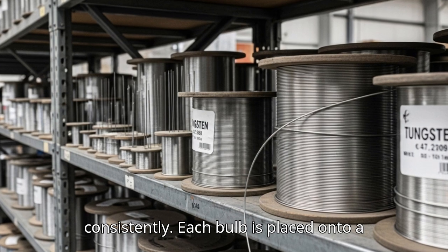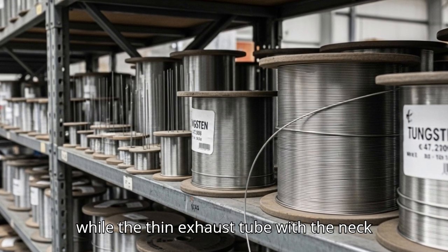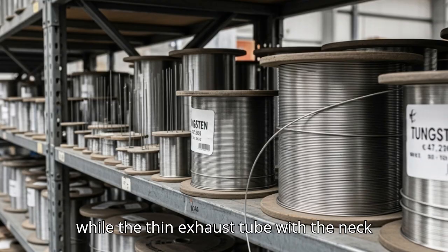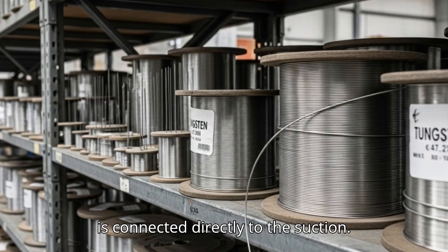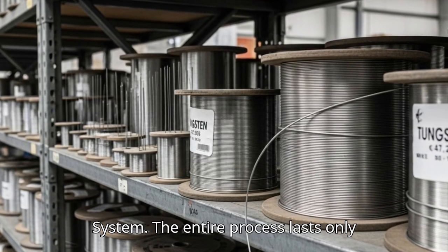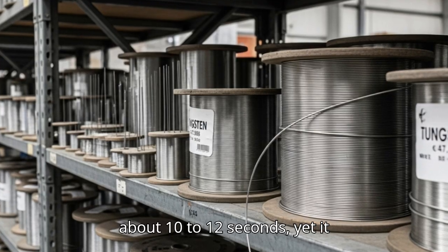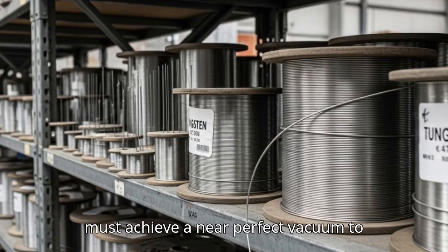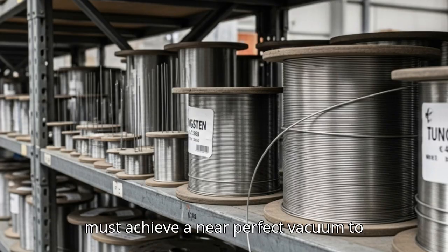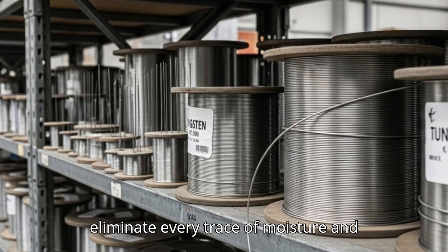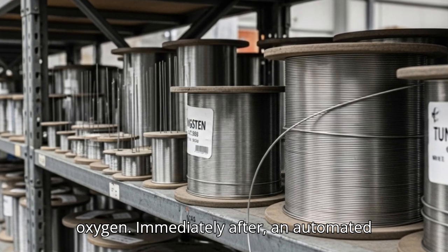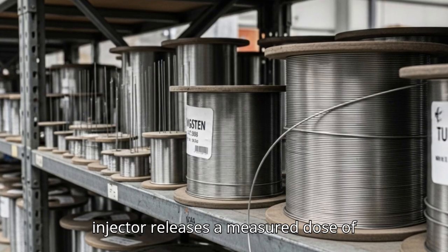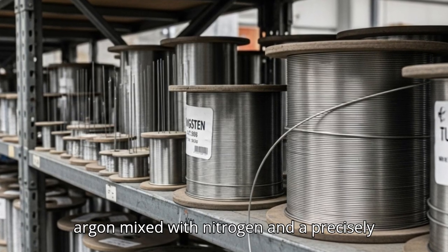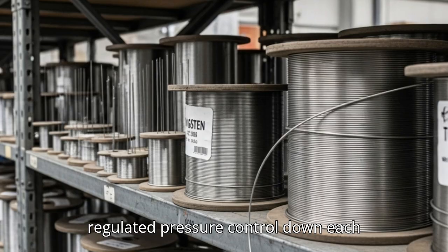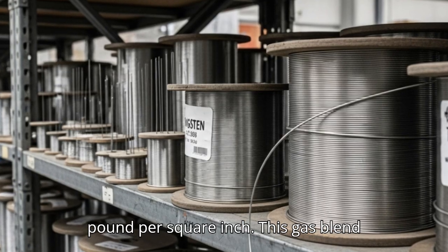Each bulb is placed onto a vacuum pump head lined with a rubber gasket, while the thin exhaust tube at the neck is connected directly to the suction system. The entire process lasts only about 10 to 12 seconds, yet it must achieve a near-perfect vacuum to eliminate every trace of moisture and oxygen. Immediately after, an automated injector releases a measured dose of argon mixed with nitrogen at a precisely regulated pressure, controlled down to each pound per square inch.